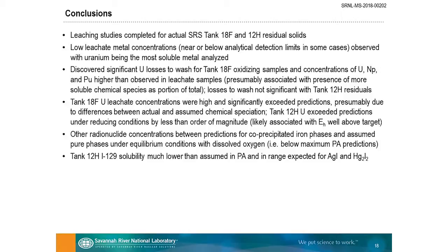Other conclusions, we completed the leaching studies. They're really kind of the first of their kind. We observed low metal concentrations, sometimes very near analytical detection limits or even below. Uranium was the most soluble. The iodine solubility was much lower than assumed in the PA. I told you they really acted like it had no solubility limits. It was infinitely soluble. But actually, we observed solubilities in the range of silver iodide and mercury iodide, which were quite low. And really, I couldn't measure them for most samples.